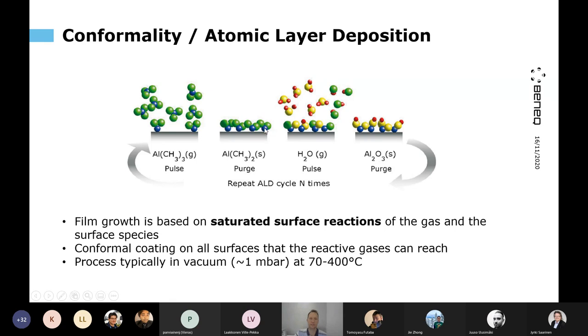Then at this point, we purge the system so that we flush it with nitrogen to get the remaining TMA molecules away from the gas phase. And then we can introduce the second reactant here, which in this case is water, again as a vapor. And that will start reacting with the surface again. And it will also continue as long as there are reactive sites available. And eventually the surface will be saturated with that reacted water. So there will be OH groups on the top. And this way, we have completed one ALD cycle.